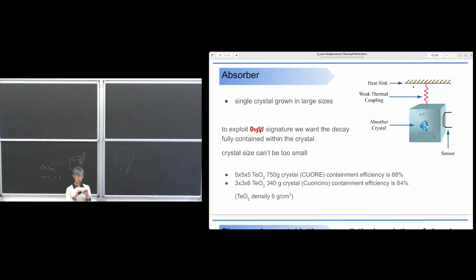We had problems on the crystal surfaces that were not clean, because when you polish them, you use powder that often introduces radioactive contaminants, but the bulk was not bad. And they were already growing those crystals for different purposes. It has optical properties that are useful for commercial purposes. So the solution for the absorber is to use a single crystal grown in large dimension, because you want to reduce the number of crystals in your array. If you have to operate a 1 ton source, you don't want to use 10 to the 6 crystals.